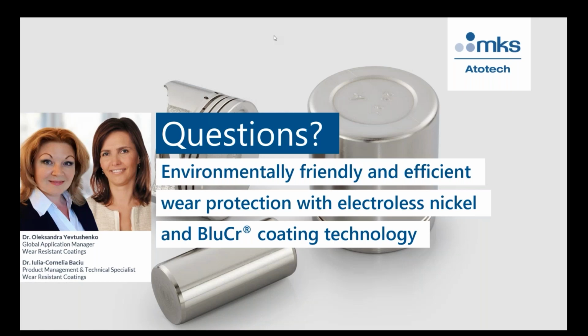Next question is regarding BluCr. Which kind of internal stress has BluCr? I will take this question. The BluCr has tensile type of internal stress over the whole time, and that is basically why we also recommend that the nickel undercoat we were talking about has also tensile type of internal stress. Why? Because the BluCr, as each chromium process, during the plating or after the plating, the chromium layer tends to release the stress as soon as possible, and this is why in case of BluCr these cracks are forming.